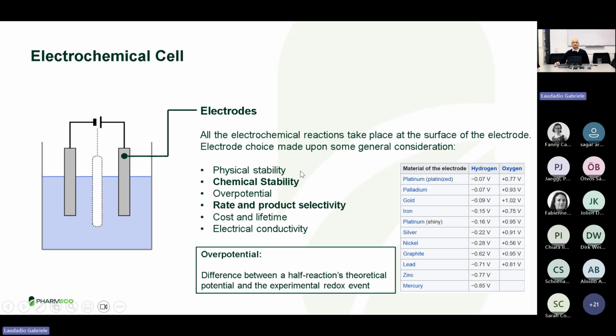Another parameter that is very important to take into account when we are selecting the appropriate electrode material is the overpotential, which is defined as the difference between the half reaction's theoretical potential, so the ones that we can find, for example, in tables in our textbooks or on Wikipedia, and the experimental redox event. So the potential that is actually measured for the same transformation. There's a discrepancy between the theoretical and the experimental value, and this is reported for many of the common materials that we can find commercially available.